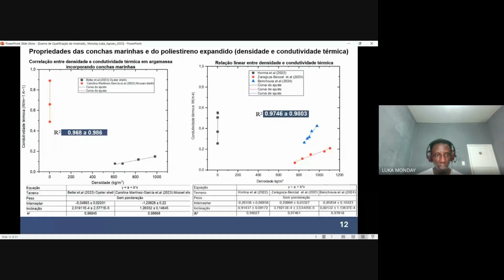Also, checking the correlation between density and thermal conductivity with respect to both materials, which are seashell and expandable polystyrene, it is clearly seen that yes, density also plays a key part with respect to thermal conductivity of any of these materials. A linear correlation was achieved. An R square of 0.96 to 0.986 was obtained with respect to seashell from the statistical analysis as shown, which clearly shows that yes, density clearly plays a key part with respect to thermal insulation when using seashell as an insulation material.